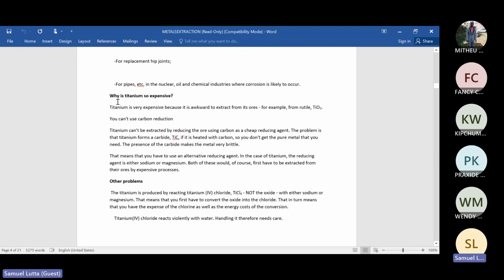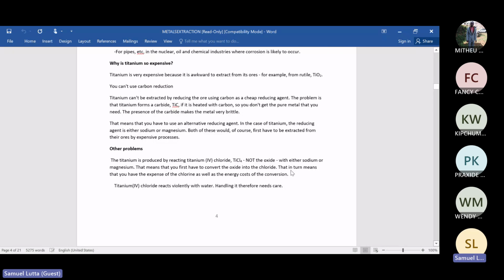because when titanium particles pack, they leave open spaces between the particles which can be occupied by carbon. So because of the formation of this carbide, it is not possible to reduce titanium oxide to form titanium. You'll get titanium carbide. So because of this, it makes the process expensive. It has to be extracted in a different way.